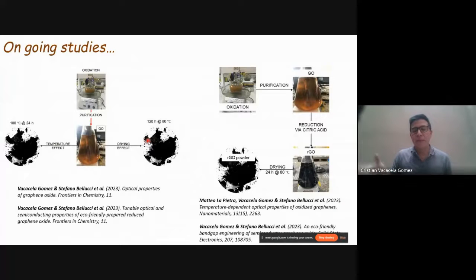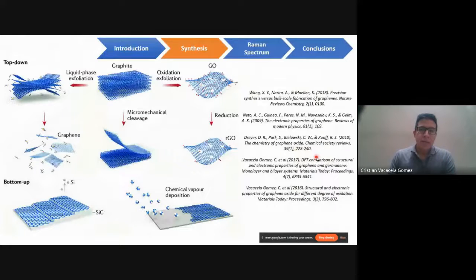What happens when we increase the time? The similar thing: once we have the graphene oxide dispersion after the reduction, again we have a reduced graphene oxide dispersion, and we can apply a similar approach. Apply what happened with the temperature, what happened with the drying effect, etc. And all these variations in the synthesis process can affect the Raman spectra of these samples.